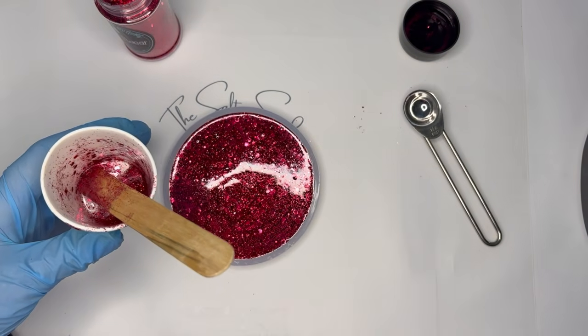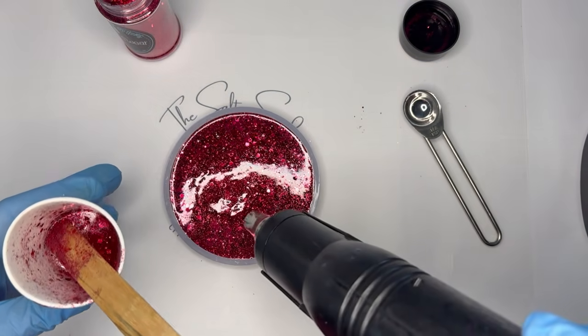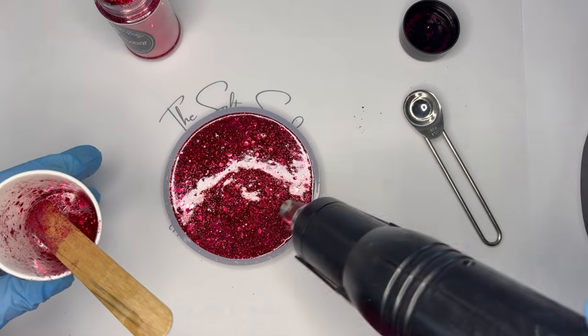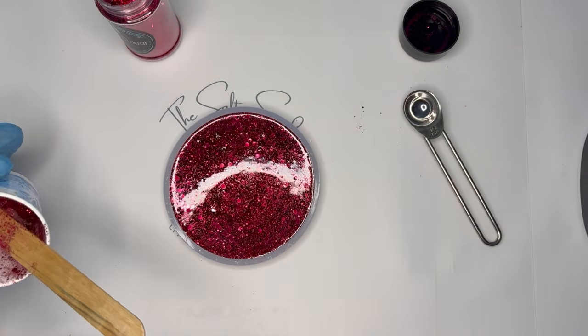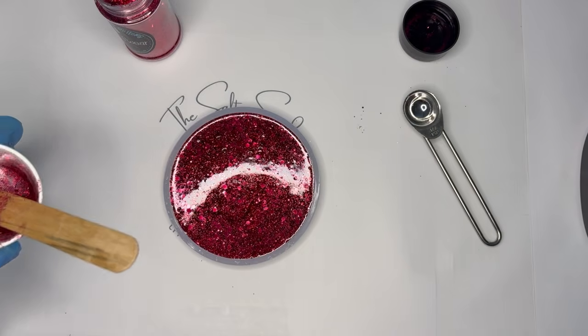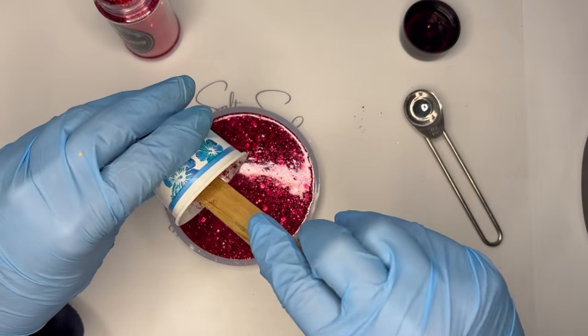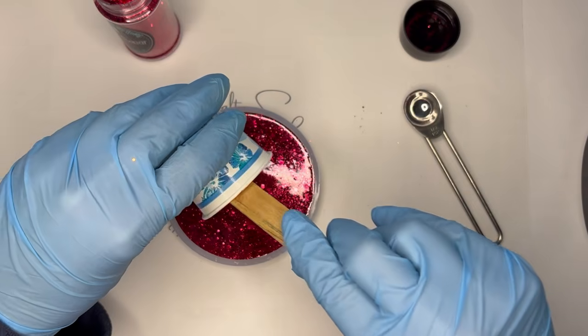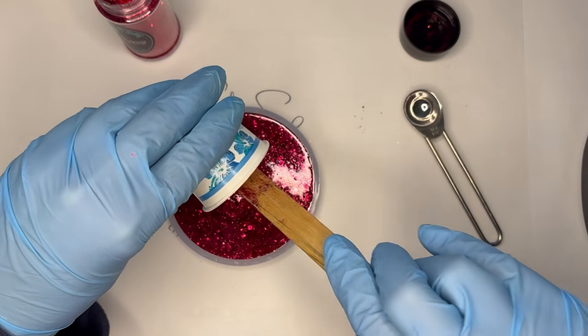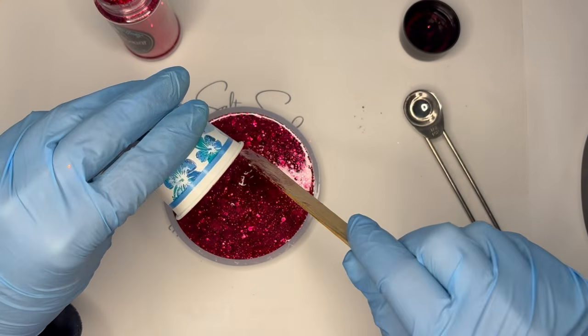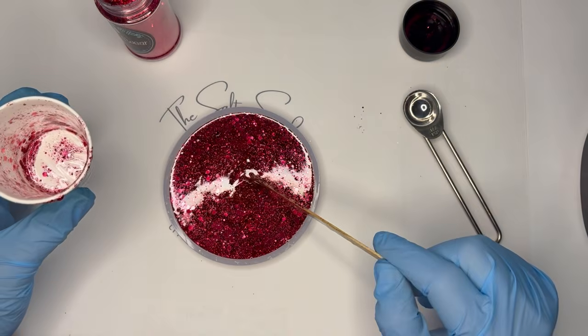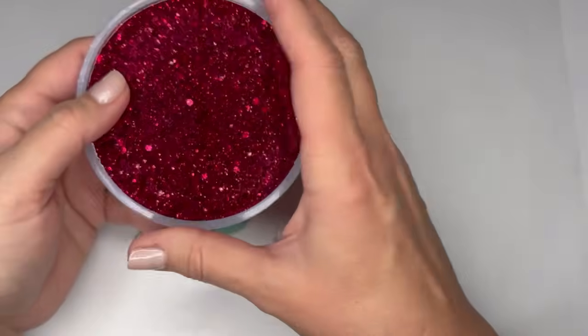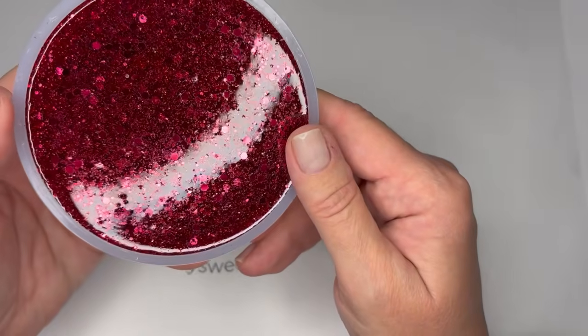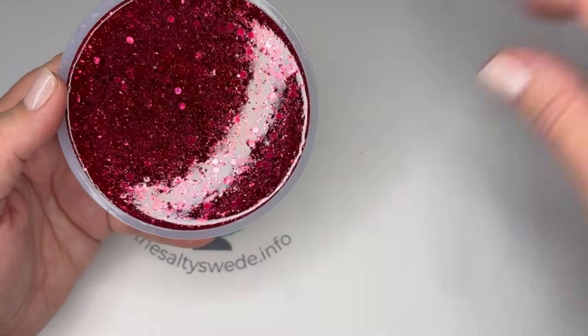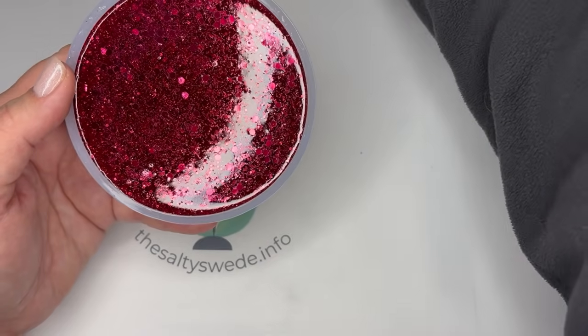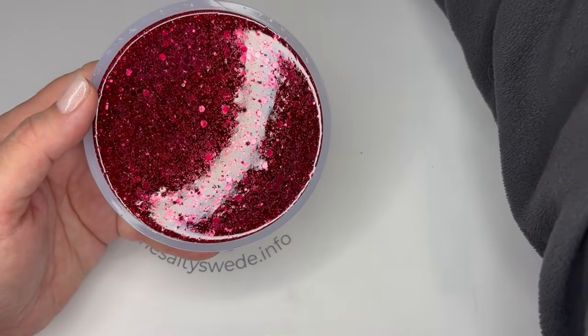At certain points, you can add things to your project like dried flowers or add a second coat of resin, but it takes some practice to know exactly when and how to do that, so save it for another day. And at some point, you'll be able to demold your resin, but each manufacturer is different, so check your instructions. If you wait 24 hours, you should be safe, unless you're using a deep pour resin, which can take several days to cure. Here we are the next day, ready to demold. The glitter looks great. It's very sparkly and not floating flat on the top, but it doesn't have a nice glassy finish like you would expect.